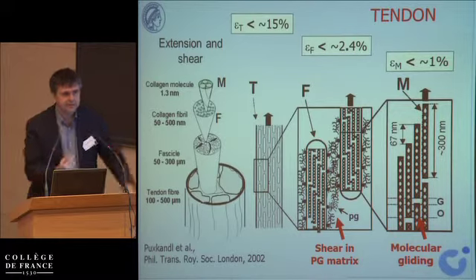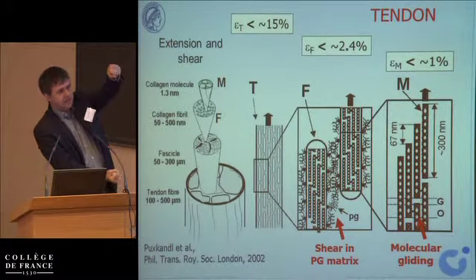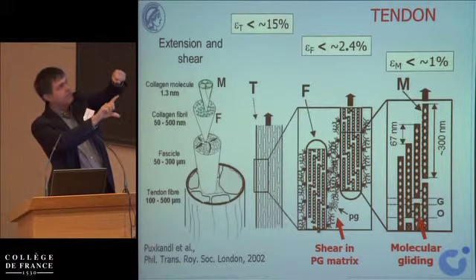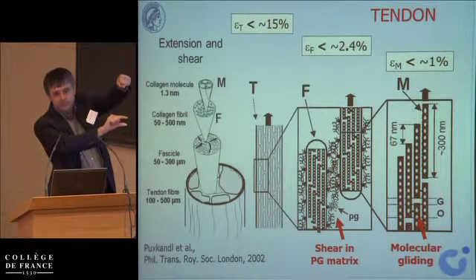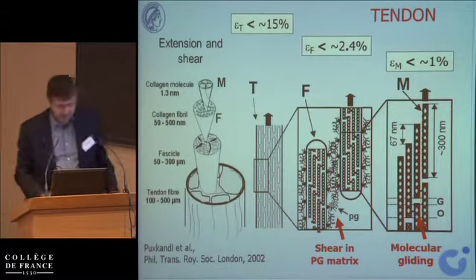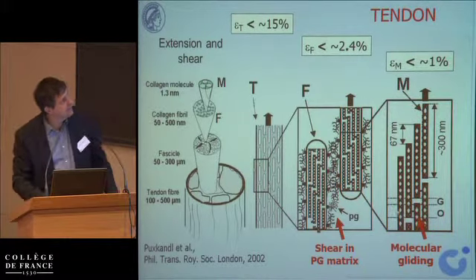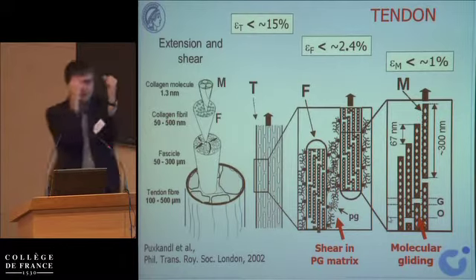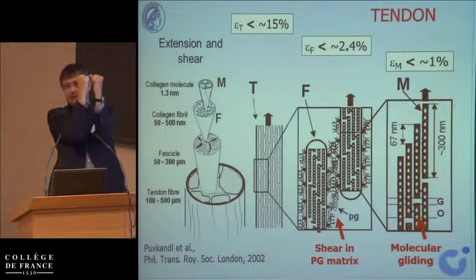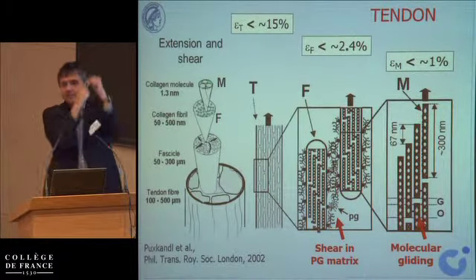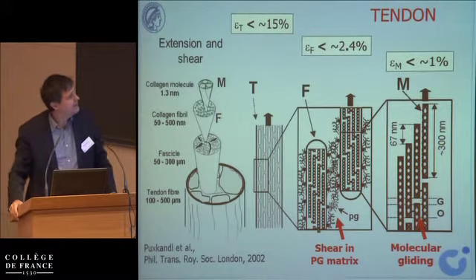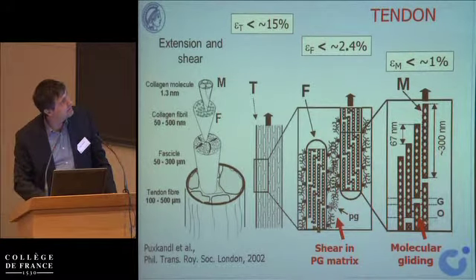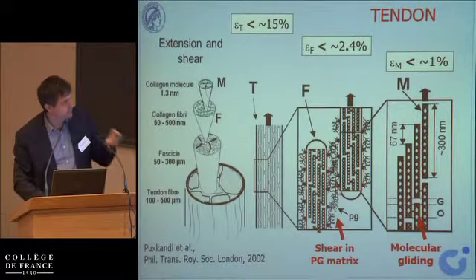So how do you make a fiber where the complete system stretches 15%, the subcomponent stretches only 2.5%, and the subcomponent of the subcomponent only 1%? That sounds strange. Well, the explanation is very simple. Well, you forget, I always need my hands for this to explain. So elongating the sum of my two hands will make me cry, but if I do this, I can easily elongate the sum of my two hands without any pain. And this means that shear between the fibers is the clue to this.